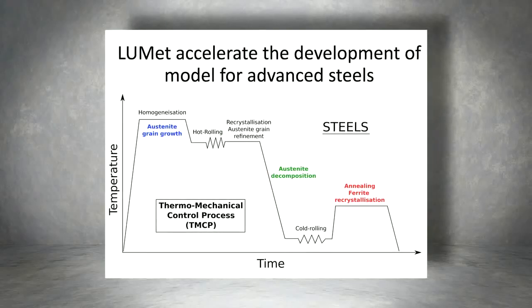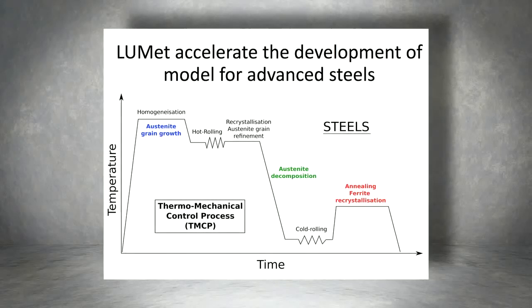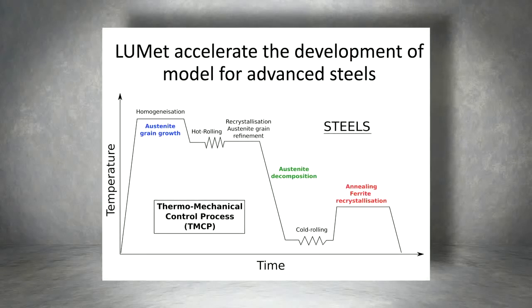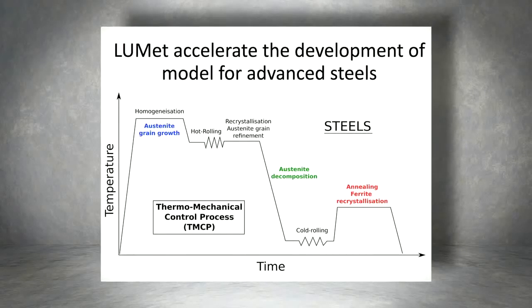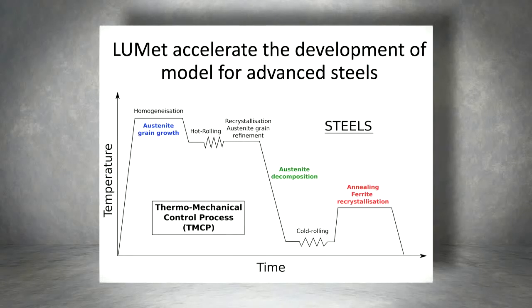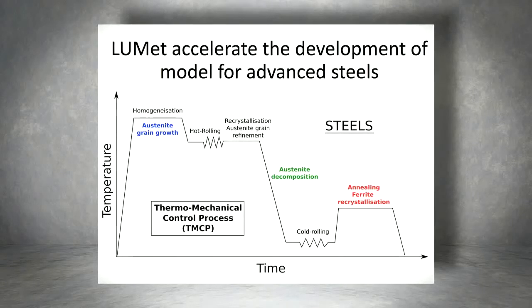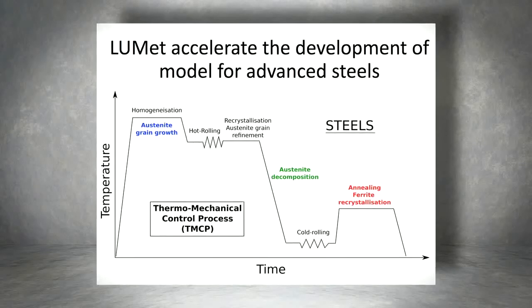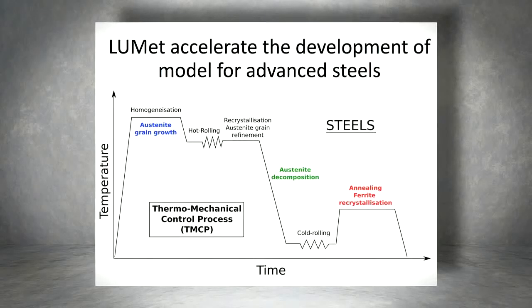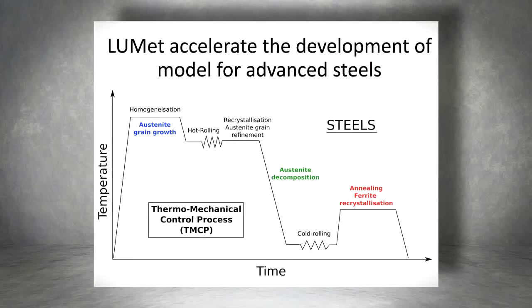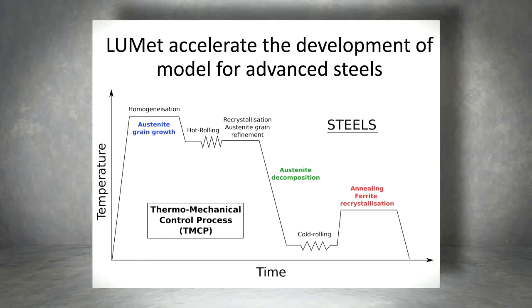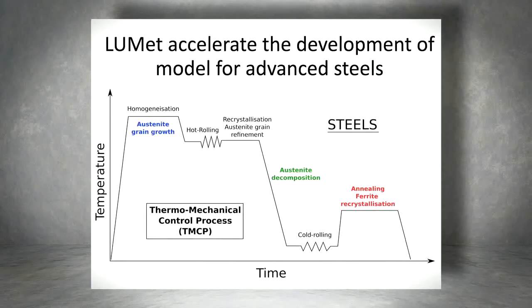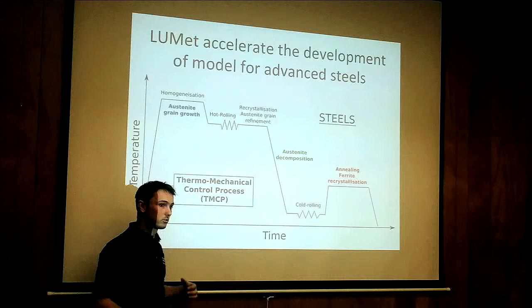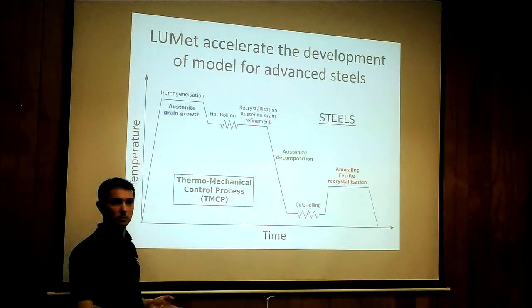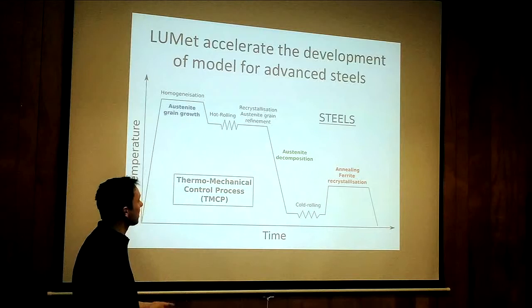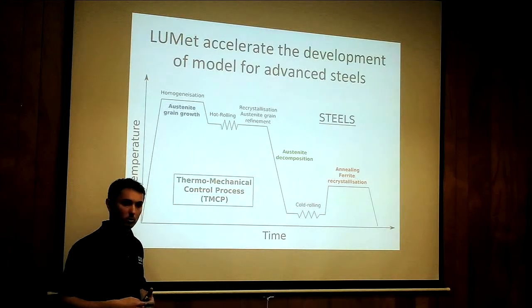So finally, I'd like to show this here. It's like a conventional thermomechanical control process where you have whole lots of phenomena which occur in the steel. At high temperature there would be austenite grain growth. At intermediate temperature during the stage of hot rolling there would be dynamic phenomena. During the cooling there would be an austenite decomposition. And finally after a cold rolling you could have a post-annealing in which the recrystallization would occur. And so LUMET can monitor most of those phenomena and so can accelerate the development of models for the development of advanced steel.